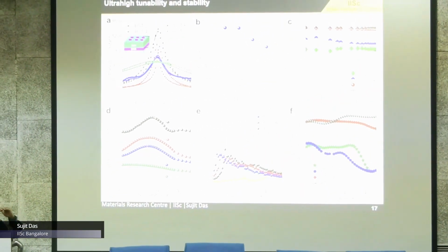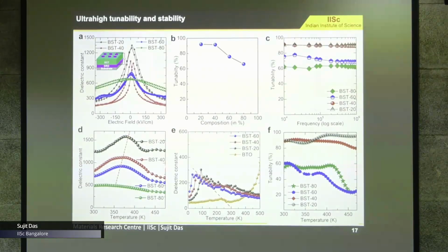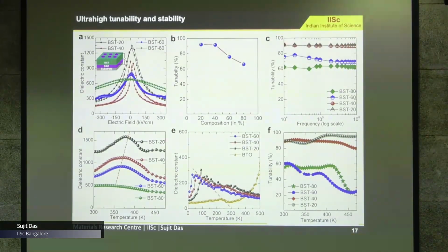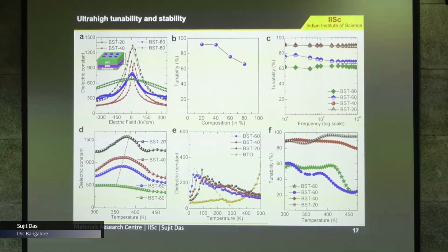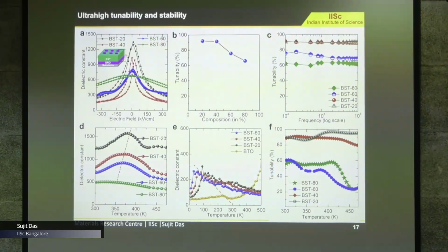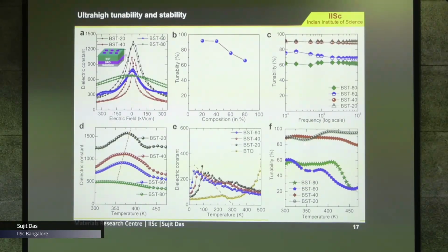Once we measure the dielectric constant with temperature, we found the phase transition is very broad and does not follow the Curie-Weiss law. So it is relaxor-type behavior, and that is further confirmed by our theory using the effective Hamiltonian model, which also shows a broad phase transition. And once we check the temperature stability, BST20 particularly shows very stable behavior up to 500 Kelvin with respect to the other compositions.